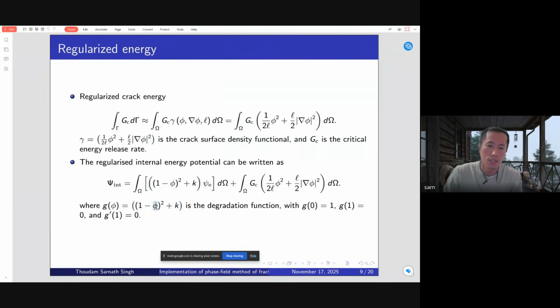And here phi is our phase field variable. This ranges from 0 to 1. If this value is 0, that means there is no damage in the material. And if this value is 1, then the material is completely broken. So when phi is 1, this term becomes completely 0. So when the material is completely broken, there is no elastic energy stored in the material. Notice that this phi is what I have shown earlier. When this phi value is equal to 1, the material is completely broken.